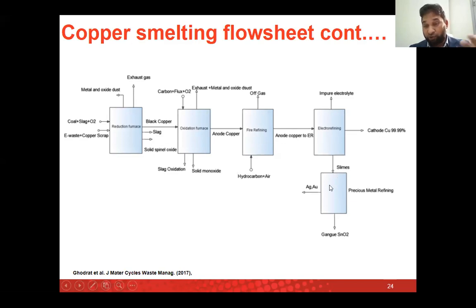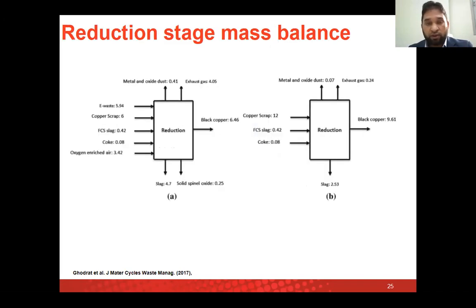This is the flow sheet for that process. So we have the gold and silver gangue, and the tin oxide from there, because tin remains there at the end, because you cannot do the oxidation of that one. You cannot volatilize that one, unlike volatile elements, for example zinc, which can be easily removed, because zinc becomes oxide and becomes volatile. So this is the flow sheet diagram.